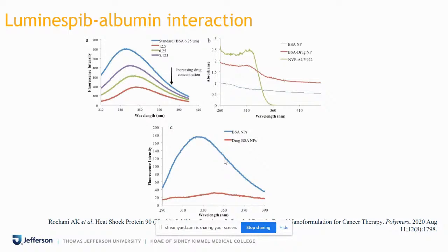But we wanted to further confirm this using UV visible spectroscopy. In figure B, which you can see over here, the green spectra is the absorption maximum coming from the NVP AUY922, also called luminespib. You can see the red spectra, which is from the drug BSA nanoparticle, and the blue spectra, which is a straight line and doesn't have any drug in it. This was again a confirmation that the drug was present in the drug BSA nanoparticle when it interacts with the albumin.